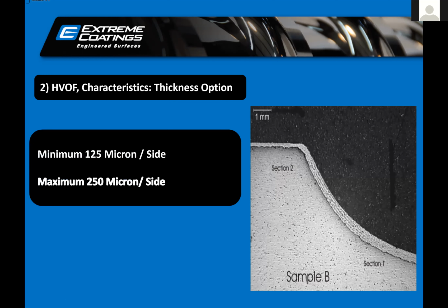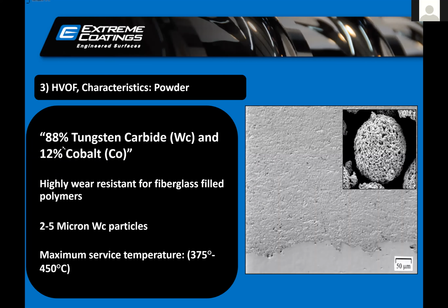The other advantage is that unlike PVD coating where only 10 micron coatings can be given, here we can go 125 micron per side up to 250 micron per side. That's the capacity of the technology. We can put a much higher layer of tungsten carbide on the top of the screw as well as on the sidewall of the screw. The third advantage is that the most advanced bimetallic technology had 25% to 30% tungsten carbide. Here the powder we are using is 88% tungsten carbide, which is almost 3 to 4 times better than whatever was available globally. So our coating is considered a super bimetallic coating, which gives double the life of bimetallics.